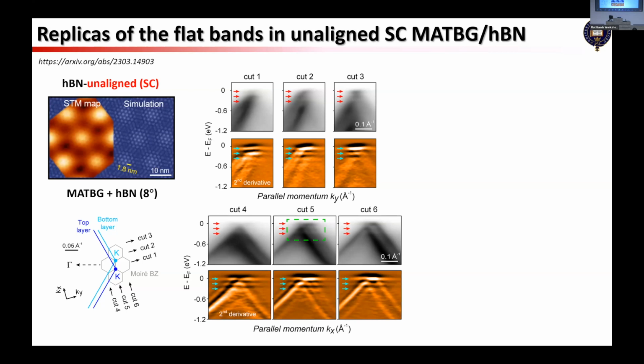And now we can see that in the raw data, we use the second derivative to enhance this effect, and you can clearly see that there are three sets of flat bands, and the top one is the intrinsic flat band, and the lower two, as we will talk about later, are the replicas from the intrinsic flat band.